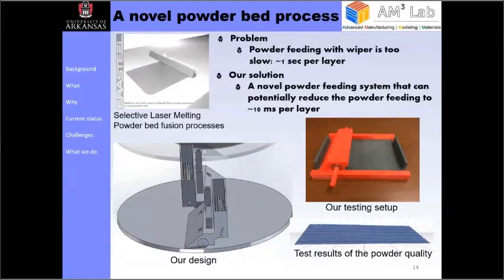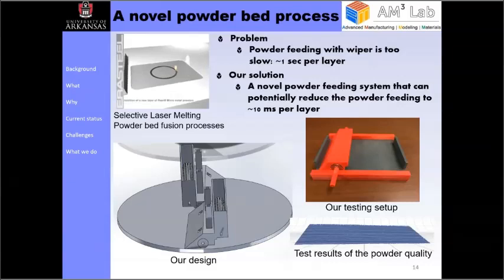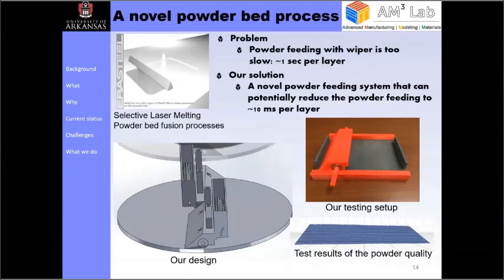So another different problem for this selective laser melting process is the powder feeding process. And you have this wiper that wipes across this powder bed to spread a layer of powders. And it's actually a very slow process because the wiper needs to accelerate and wipe and then decelerate and stop and then change direction and do it again. So it takes about a second to spread one layer. And if you are going to do thousands of layers, it's going to be hours.